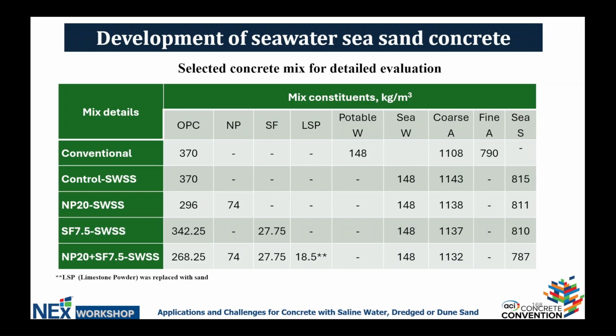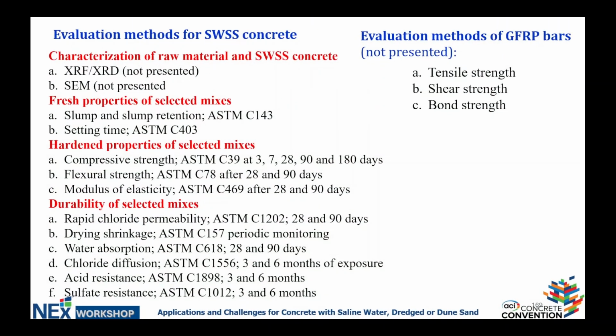So PW for the potable, then the seawater, then the coarse aggregate was the same for all of them, whereas the fine aggregate was, in the case of the conventional mix, regular sand, mine sand, and then the sea sand is for all the other mixes. Obviously, in the first column, you see the mix details, and the acronyms are pretty clear in terms of what they mean in terms of constituents.